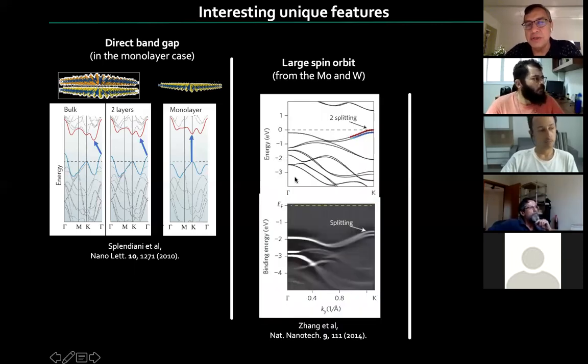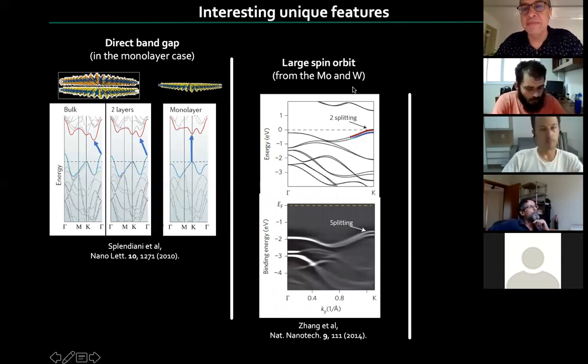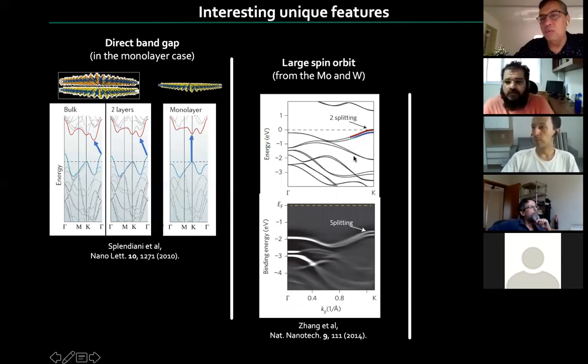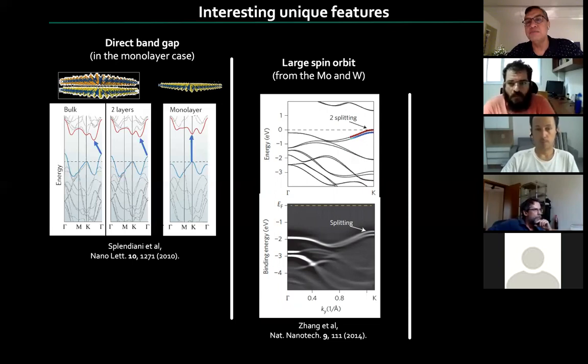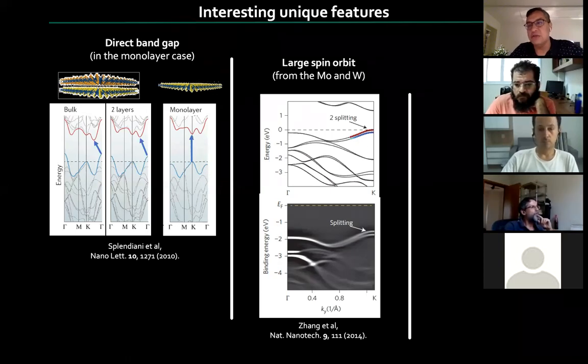One interesting feature of these materials is that, because they include moly and tungsten, which are heavy transition metal atoms, there is a strong spin orbit coupling, which results in a splitting of the valence band, for example, that is rather large, on the order of 100 or a couple hundred millielectron volts. This is much larger than in other semiconductors like indium arsenide or gallium arsenide, where a spin orbit of 10 millielectron volts is large, right? So in that respect, this is a very different kind of semiconductor from the spin orbit point of view. And it has advantages and disadvantages, of course.